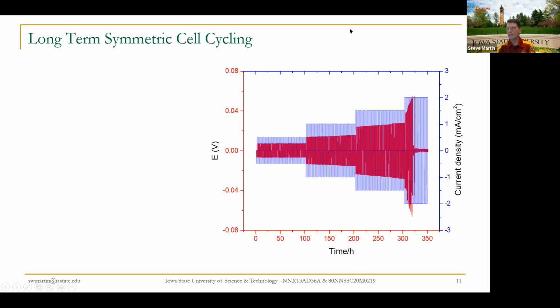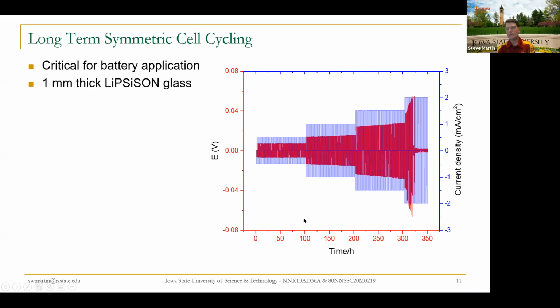Just to show you that we can cycle these things a long time. This is hundreds of hours. In real use it would be thousands of hours, but for NASA, hundreds of hours of missions is okay. This is almost 1,000 cycles, and that's typical. A couple years of cycle life is really all we need. Automobiles, right? You would cycle them every day and use them for 10 years. That would be 4,000 cycles. This wouldn't work for them yet, but it works well for the types of applications that NASA needs.